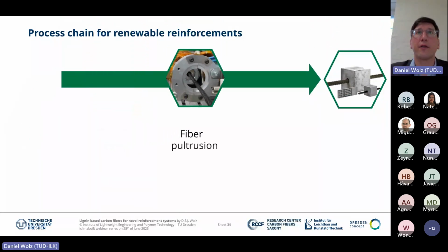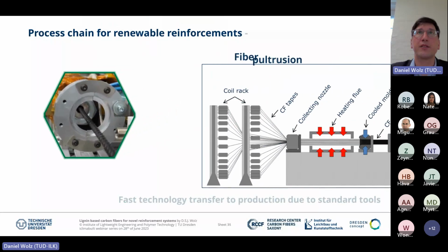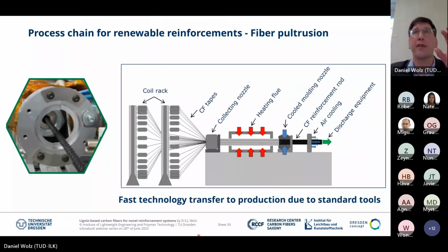If we look at the manufacturing, afterwards, on fiber pultrusion, we need polymer reinforcement rods made by fast process technologies. At ILK, we developed, in cooperation with partners of C-Cube, a pultrusion process where we have a first coil rack, afterwards the CF tape collection, a collection nozzle to bring them together, the heating device, a cooled molding device, afterwards the CF reinforcement rod, and air cooling and discharge equipment.